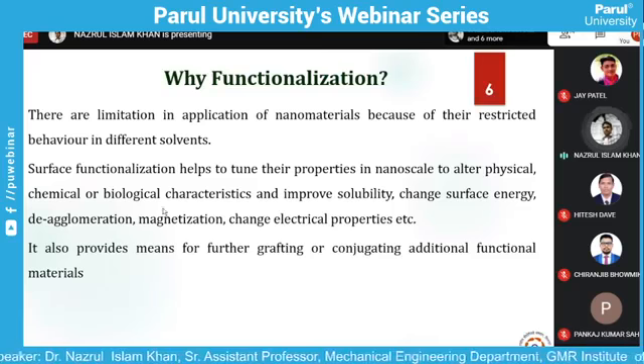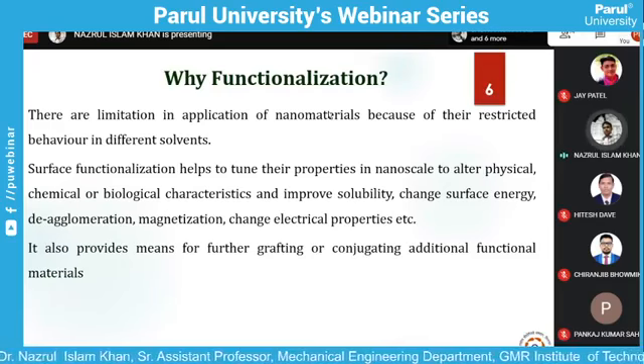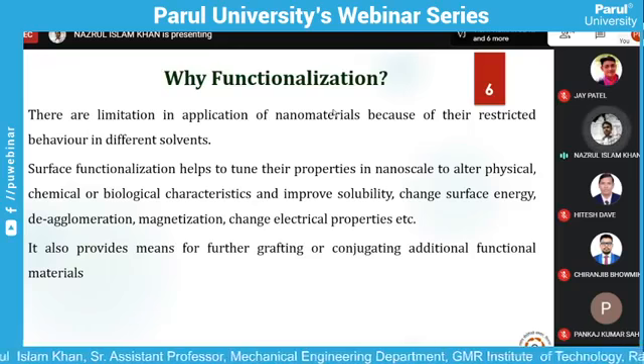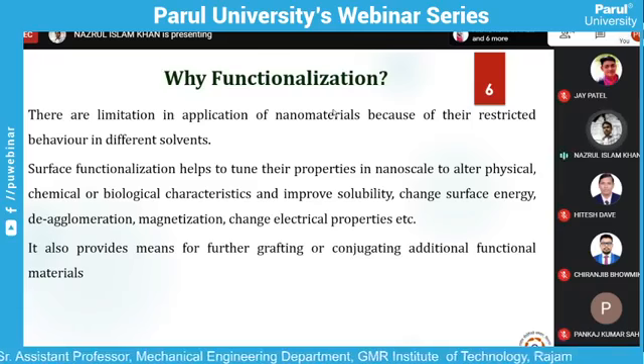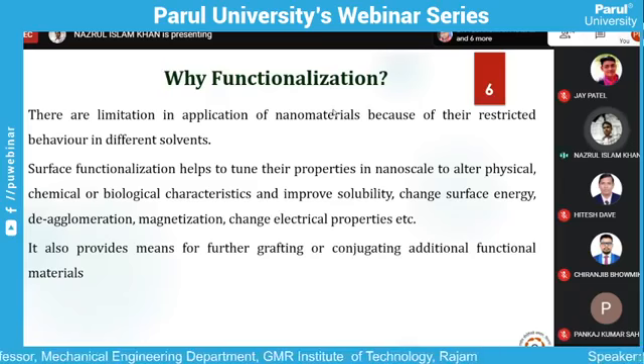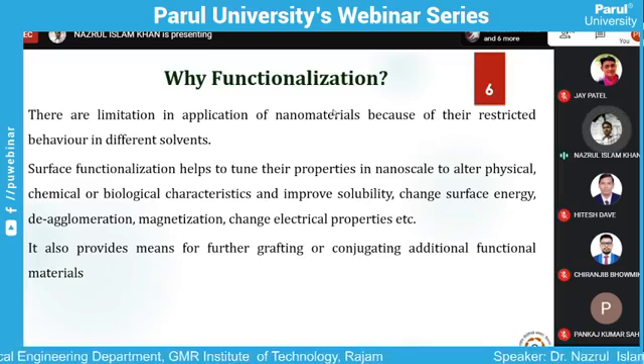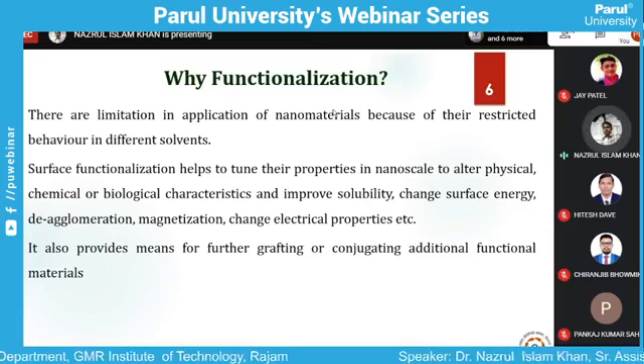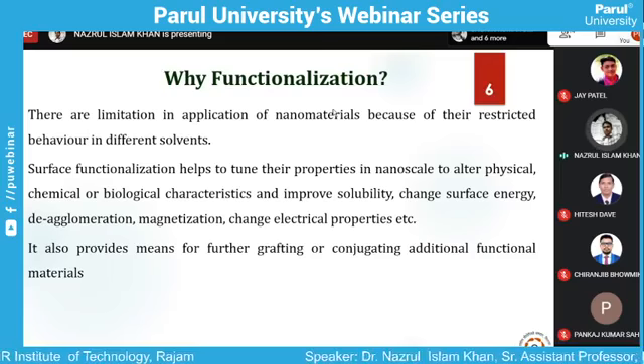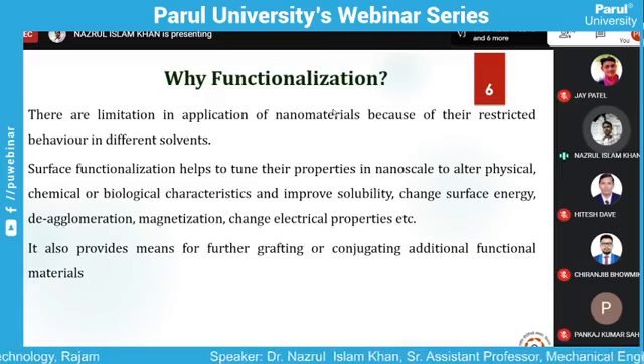In the case of polymers also, there are limitations in the application of nanomaterials. In the field of nanotechnology, the nanofillers have very, very high surface energy, and that's why these nanomaterials don't have good interaction with the matrix material. The polymer matrix doesn't have good interaction, or has bad wettability, you can say. So to increase the wettability of the nanofiller with the matrix, or to incorporate certain electrical or thermal properties in the material, we can go for this kind of functionalization.